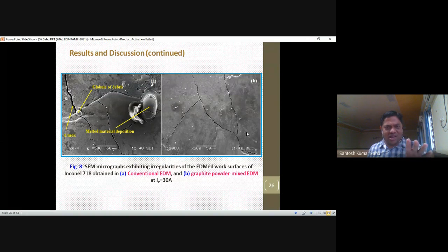You can see how a small amount of powder, when added into the dielectric, significantly minimizes the debris and the cracks. Yes, cracks are there, but the severity of cracks is clearly reduced when you add graphite powder, and to some extent the metal deposition is there. It should be eliminated by the use of graphite powders. Here we also have a comparison with the conventional EDM. Some slabs of crater are there, large diameter globules are there, everything in that figure, and also wide and shallow craters that enhance the surface finish of the specimen by adding powder mixed EDM. All those things should be eliminated with the help of the graphite powders.